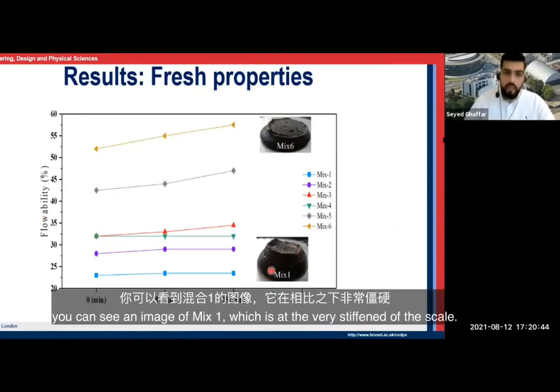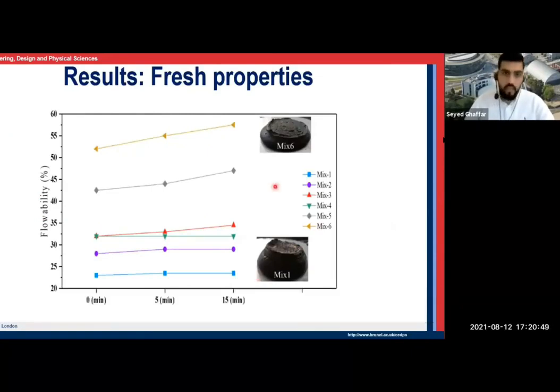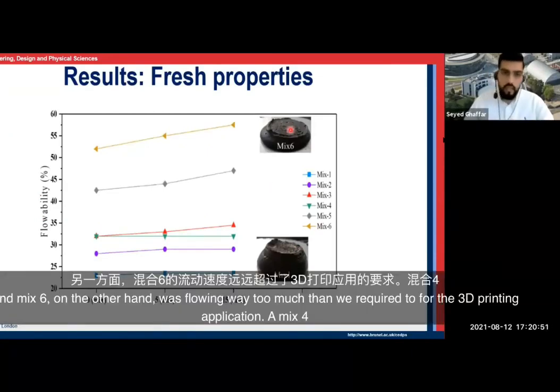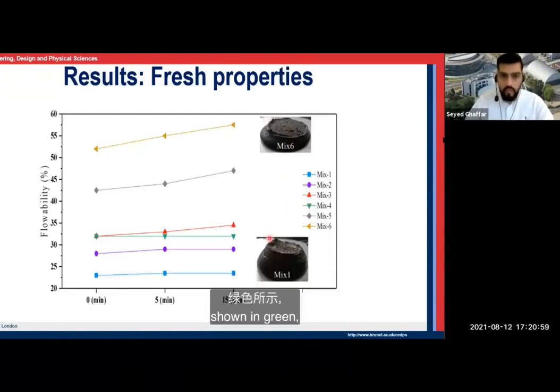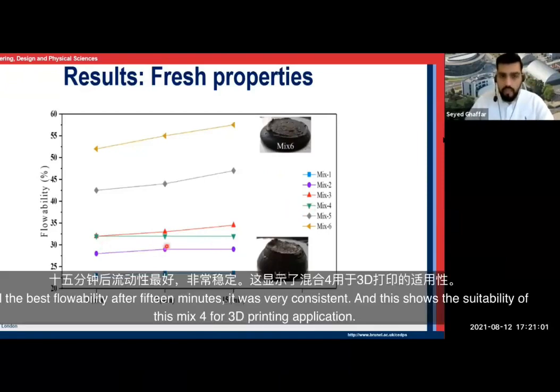You can see an image of mix 1, which is at the very stiff end of the scale, and mix 6, on the other hand, was flowing way too much than we required for a 3D printing application. And mix 4, shown in green, had the best flowability after 15 minutes. It was very consistent, and this shows the suitability of this mix for 3D printing application.